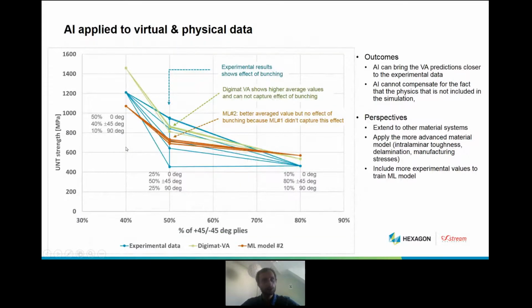So overall, once we apply artificial intelligence to virtual and physical data, what do we see? Well, we see that from an experimental perspective, we have a strong influence of the applied bunching effect. The initial simulation data points do not capture the effect of bunching because they were not yet using the ingredients that I showed you before. And once we start training the machine learning model with both simulation and experimental results, we have better average values, but we are still not able to perfectly capture the effect of bunching because the first machine learning model did not actually capture this effect.